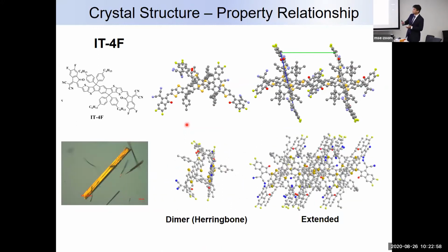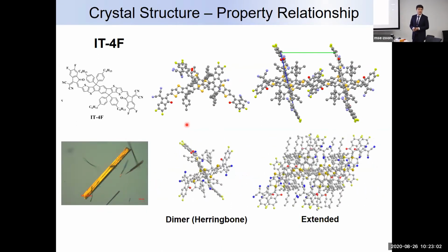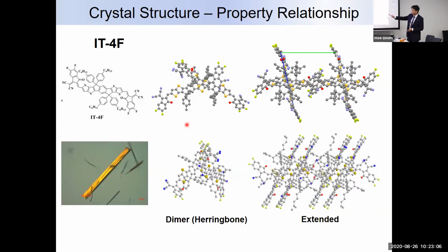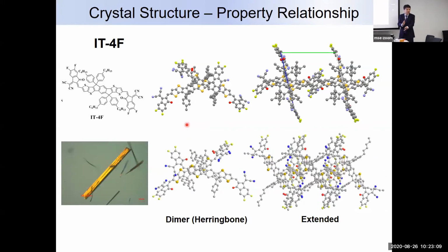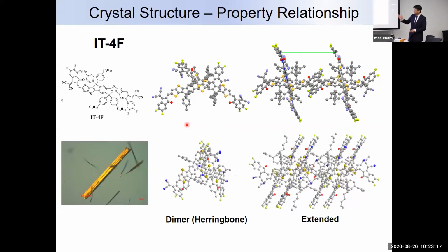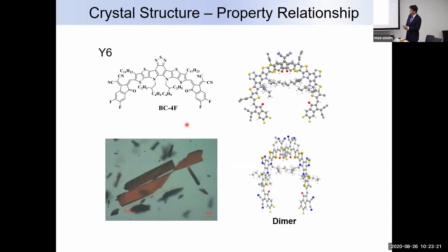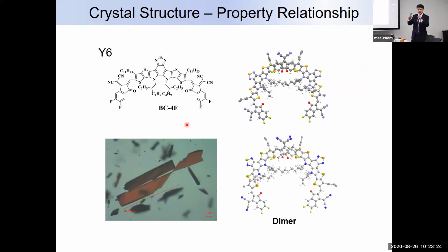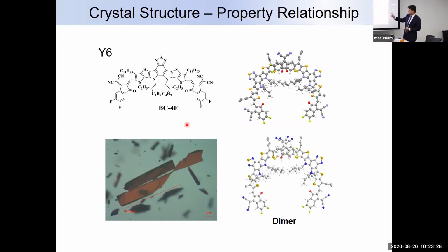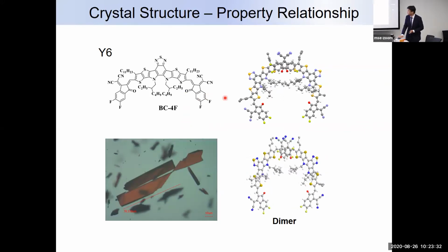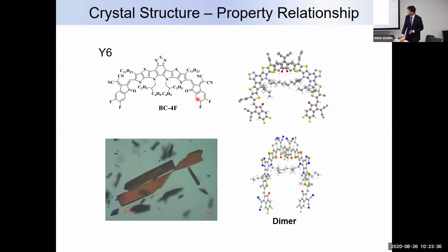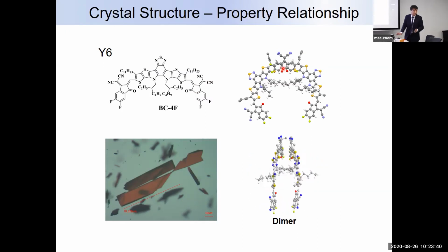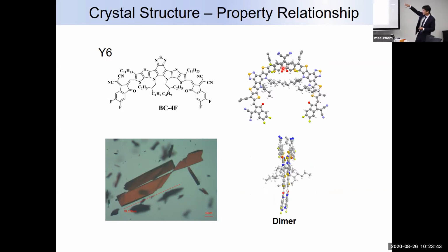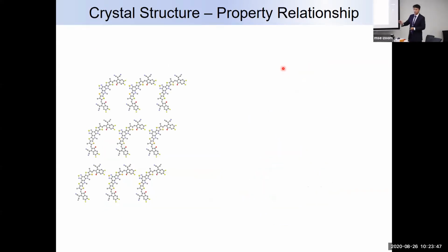crystal structure. First we look at this IT4F, which, although it showed decent performance in organic solar cells, if you look at their dimer, they don't really pack as ideally as we think, right? They are more packed like a herringbone structure. So I would say their charge transporting properties with this type of structure are not really ideal. But now when we look at the Y6, this curved structure, this is a dimer. Now it's quite interesting. They are very planar. And you can see in this dimer, the electron acceptor units are packing on each other to form this dimer structure, just like a U-shaped dimer structure. And now when we look at the extended structure, this one is the first plane of the crystal structure, okay?